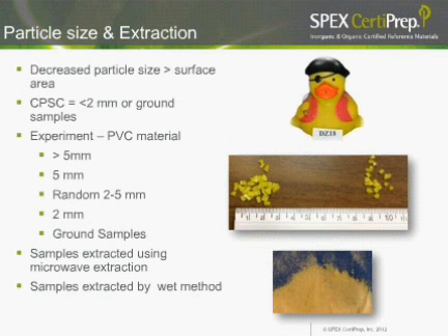One of the things we did want to know was whether there was really an advantage to the extraction by decreasing the particle size. We know that decreasing the particle size will increase the surface area for extraction, but does that really give you a better extraction than just cutting it into small pieces? Now, the method does call for less than 2 millimeters or a ground sample. So we took our PVC duck, our friend the pirate rubber duck here, and we took different size samples. We had sample sizes of greater than 5 millimeters. We had some around the 5 millimeter mark. We took some random pieces that ranged from 2 to 5 millimeters. And our prescribed 2 millimeter parts, and then finally our ground samples.